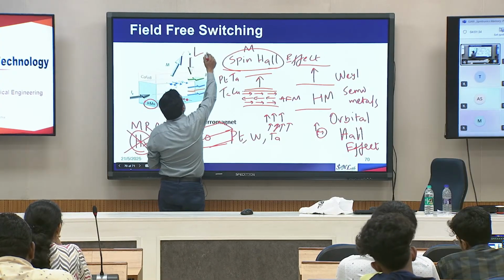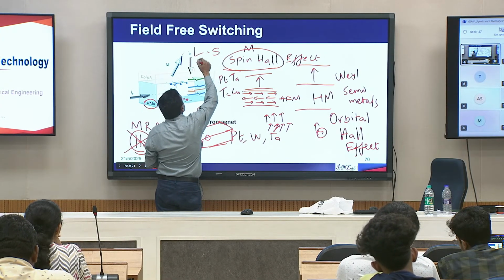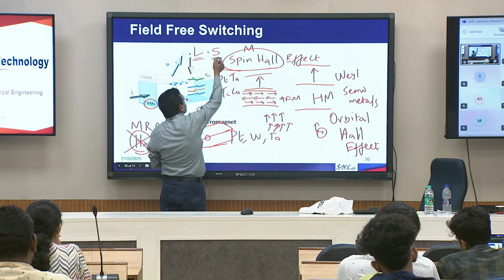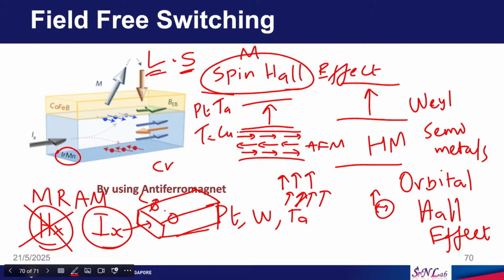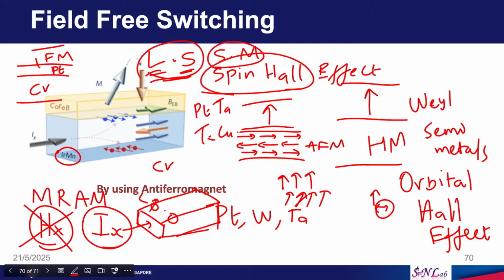So, what we do, we exploit the LS coupling. So, we convert orbital torque into spin torque through some mechanism. For example, let us say chromium is the orbital Hall layer. So, there is an orbital Hall effect. We convert that into spin Hall effect by having, let us say, a thin layer of platinum. So, we have L to S, then we generate spins that go up to the ferromagnetic layer. So, S can be coupled to M. Yes. Then with this L to S conversion we can switch the magnetization.